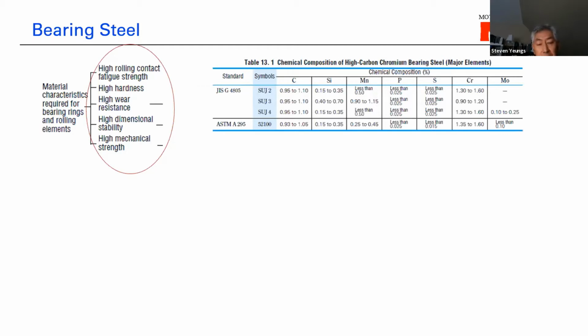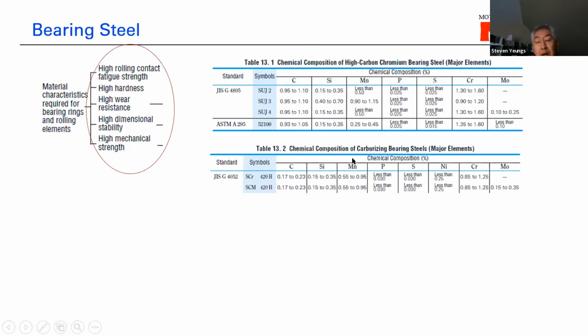The recipe is under 52100. That's the ASTM so-called spec. JIS is under Japan, the Japan Industrial Standard, so the equivalent is SUJ2, SUJ3. The characteristic is that it's basically a high carbon chromium steel. You can see about 1% carbon, and then it's got chrome in there, with additional alloys. The other one is a case carburized steel, which is opposite to the through hardened steel. It is a low carbon steel, about 0.2%, with chromium and different alloys added as well. There are many others out there.